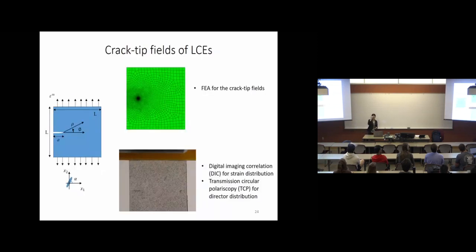So what we are interested in is the crack tip behavior. If you have a liquid crystal elastomer with such unique behavior, where the stress and the director orientation can couple together, then we ask the question: what if at the crack tip you have high stress concentration and a very highly inhomogeneous stress field? What will happen to the director field, and how will that further change the deformation and the fracture behavior of the liquid crystal elastomer?